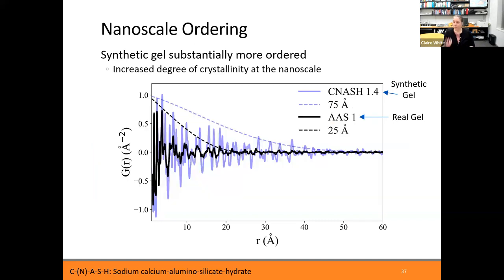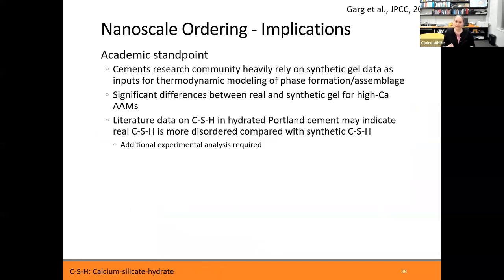A similar argument could potentially be the case here, whereby the more disordered gel, this real gel, is less thermodynamically stable compared to the synthetic gel. So we need to be careful about using thermodynamic data, and specifically things like solubility product for the synthetic gels for inputs to thermodynamic modeling, because essentially the community uses a lot of thermodynamic modeling to predict phase composition in the concrete. And the thermodynamic data for the gels comes from these synthetic gels.